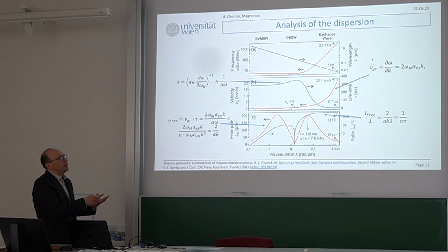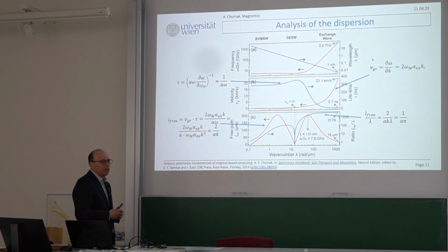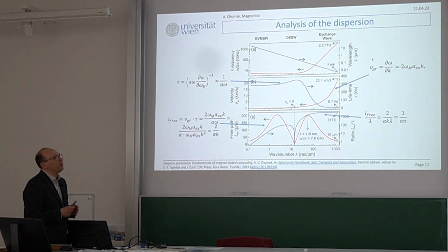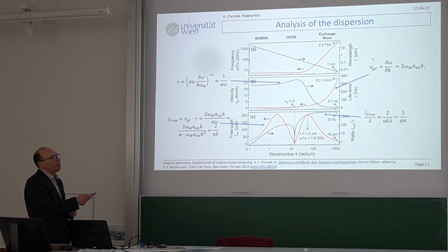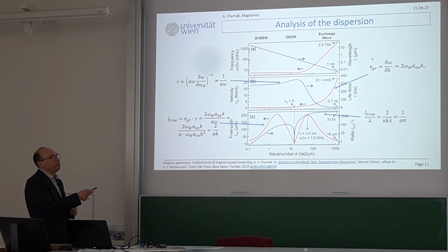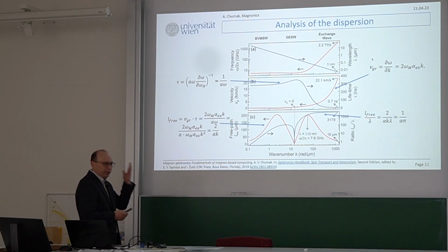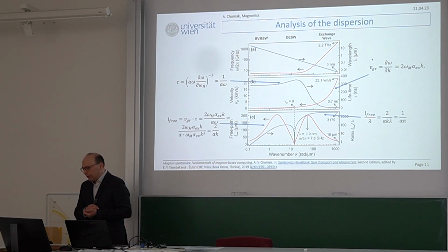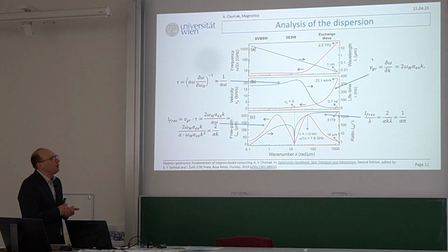For us the wavelength would be 1.2 nanometers, like the lattice constant. That's why I stopped here at 5 nanometers, just to be able to use this formula. I don't go further, but already at this wavelength in YIG, the frequency will be 2 terahertz. So we're already very high in frequency, and it's already interesting. So we can have a good overview.